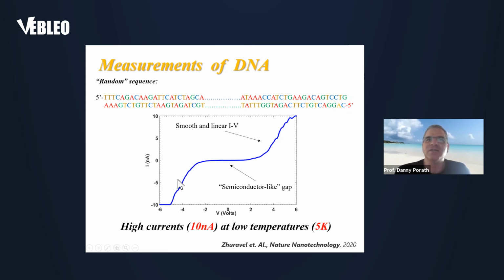We limited the system to 10 nanoamps to avoid burning the molecule. And we can get a smooth and linear or S-shaped curve. And that shows that a 30 nanometer long, 100 base pairs long DNA molecule can conduct significant current. And that's very important. It addresses the question whether DNA can conduct. Yes, it can conduct significant current. This was measured at 5 Kelvin.